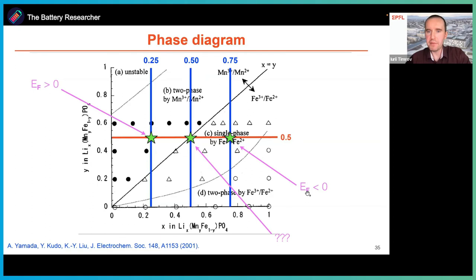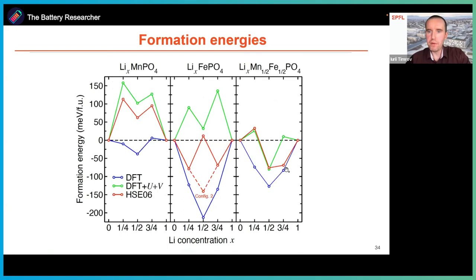And if we look at our calculations, we find that the hybrid functional gives the correct behavior and it's on the convex hull, while DFT plus U plus V unfortunately gives a result which is not consistent with experiments. The possible reason why DFT plus U plus V fails is that we neglected configuration entropy terms in the simulation. So possibly if we include them, the trend might change, but we need to verify this. But so far, DFT plus U plus V failed while hybrid shows the right solution.